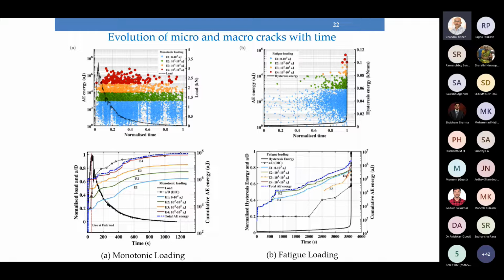So what we see is when the load has reached about 20%, or 40% or 60%, there is a surge in the acoustic emission events of all energy levels. Okay, now why does this happen? It's because we have a notched beam, and initially, because of stress concentration and also some kind of redistribution in the stress taking place at the notch tip, micro cracks are formed. Micro cracks even coalesce and form larger cracks right in the beginning.